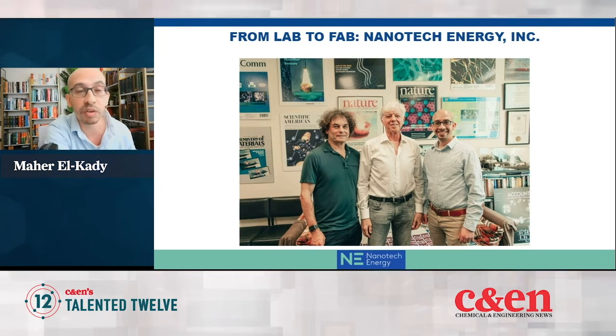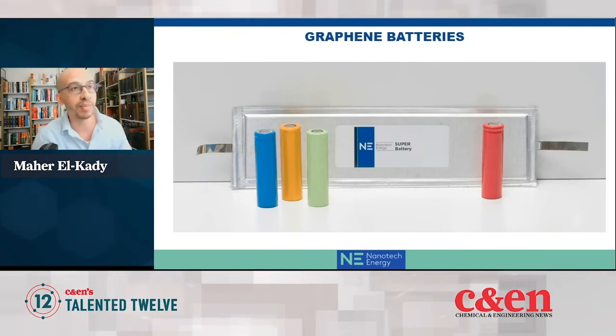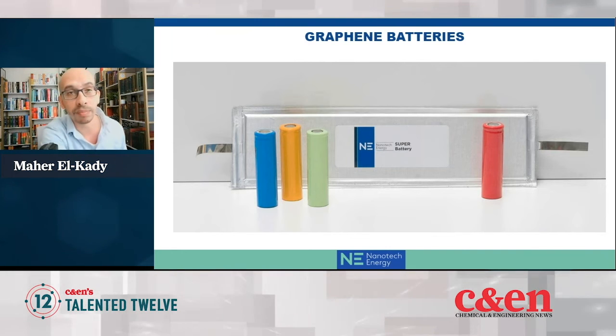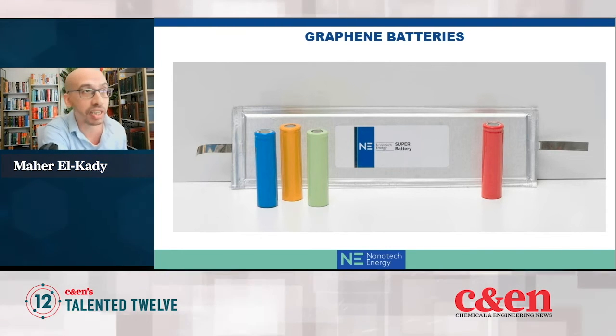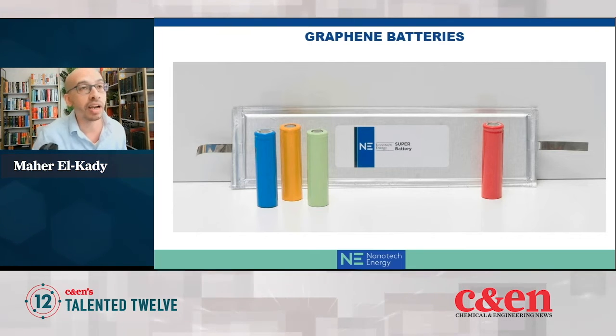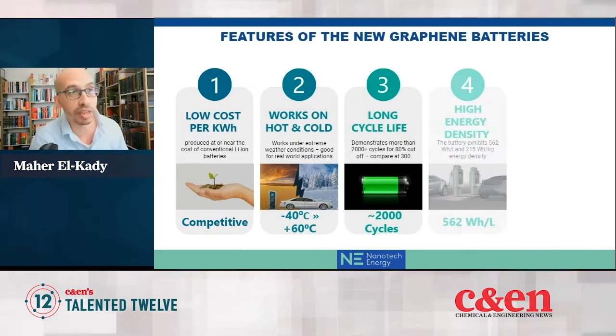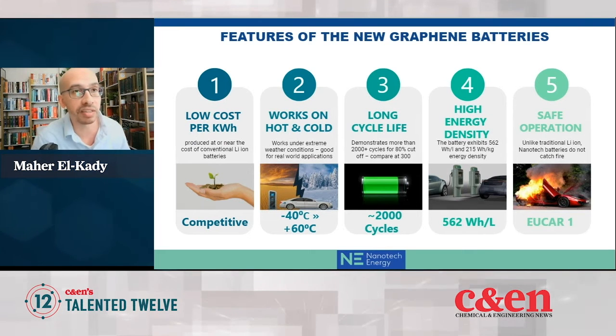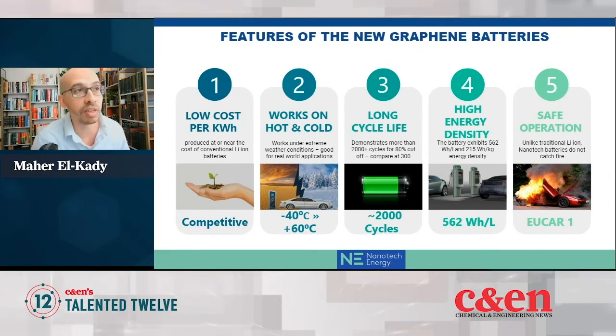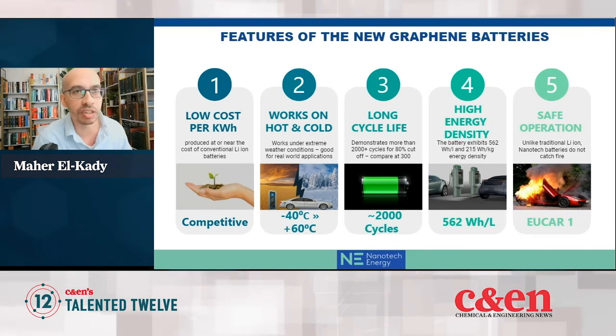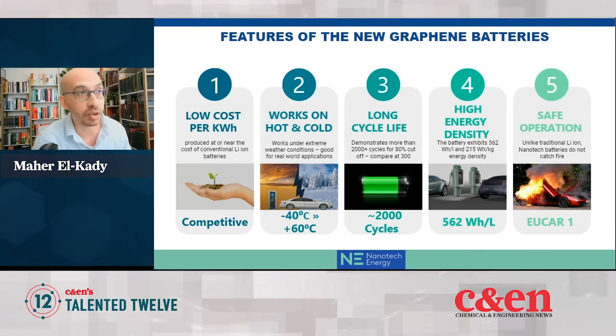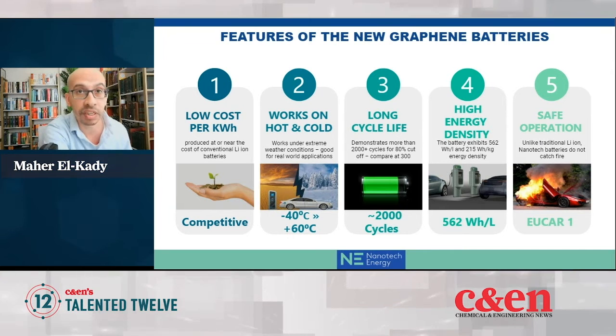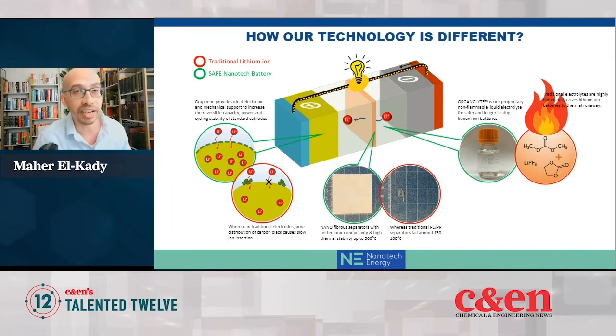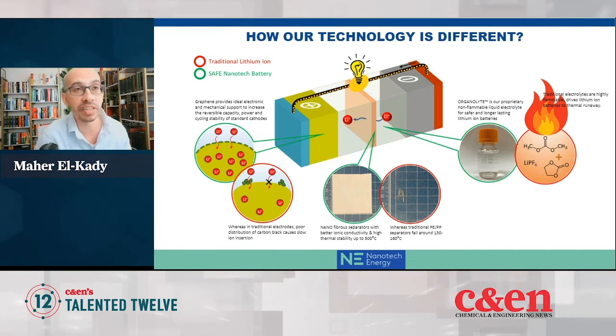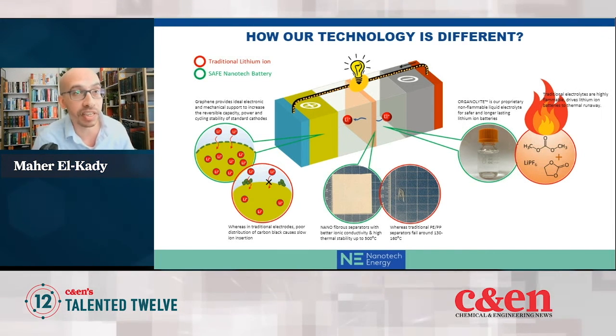And after many years of development, we now have these graphene batteries available in different form factors, like cylindrical cells and pouch cells. These batteries have low cost. They work over a very wide temperature range from negative 40 to plus 60 degrees Celsius. They can be used for over 2,000 cycles, compared to about 500 cycles for a traditional LCO chemistry. And they've got very good energy density and also safe operation. This excellent performance is attributed to the new design of the battery, where we revisited the role of the electrodes, the separator, and the electrolyte.